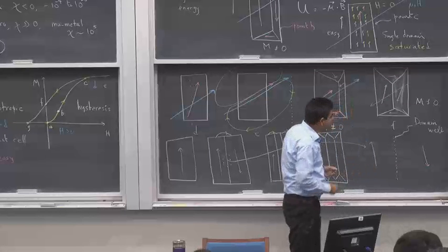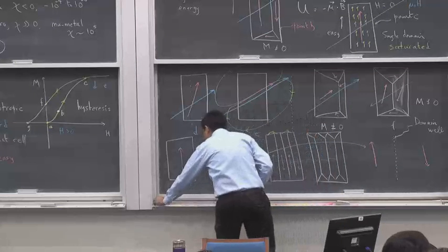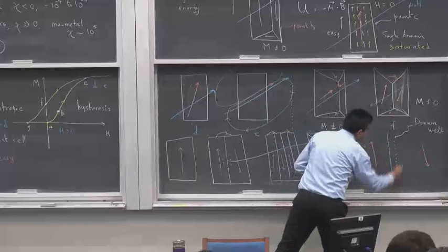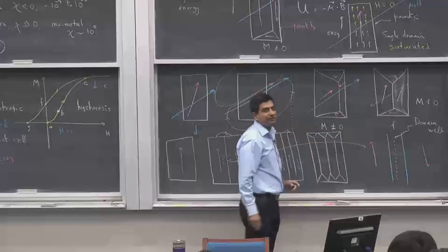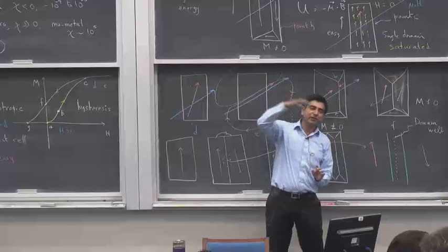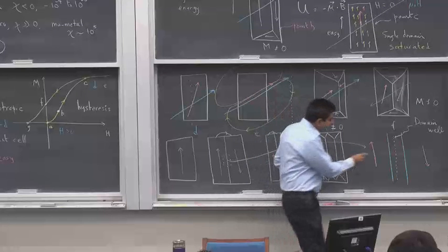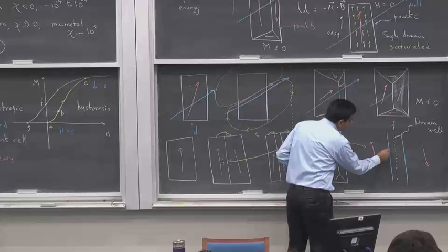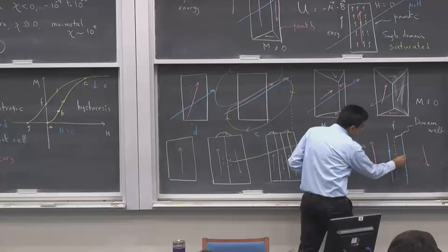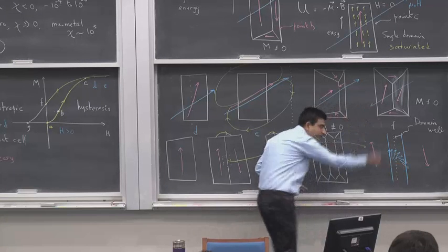So what happens is that this domain wall has a certain finite thickness, a few hundred angstroms perhaps. And the iron atoms inside this wall gradually shift their magnetization. So the iron atoms here will have the magnetizations or spins pointing up, here they will be pointing down, and in between there will be a gradual transition of the magnetic moments of the spins.